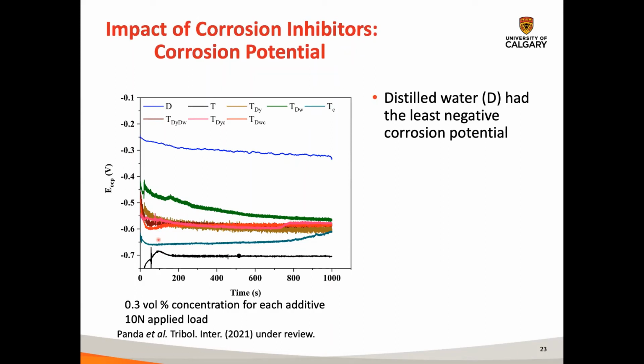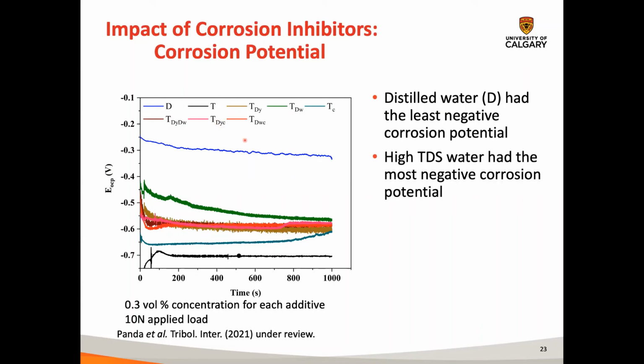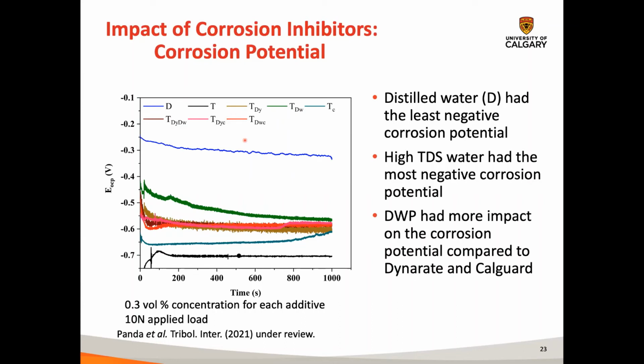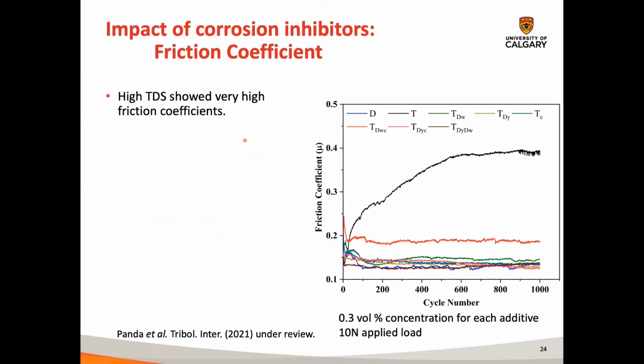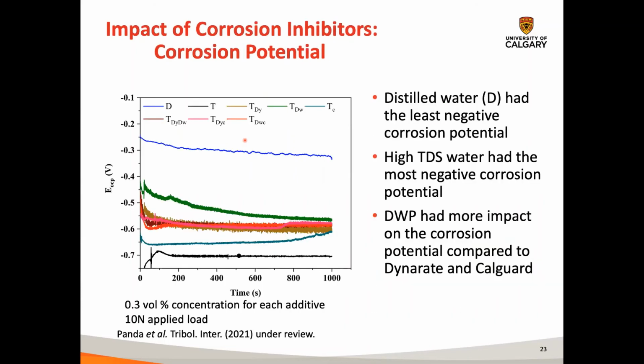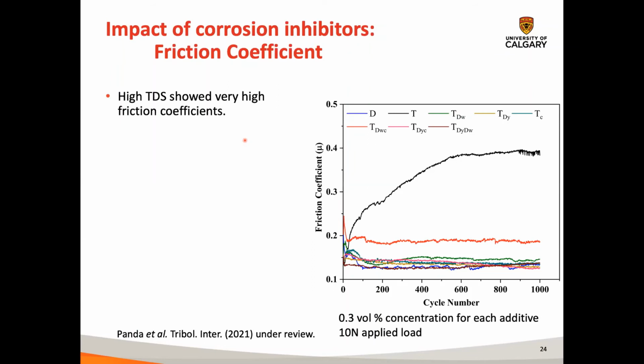And then when we put the different additives in, they did what they were supposed to. So they changed the potential, and so it's less corrosive as you add these different chemicals in. And in this case, we looked at adding both the 2 organic friction modifiers at the same time. And when you see C here, we added the CalGuard and one of the friction modifiers as well. Right, so DWP has more impact on the corrosion potential compared to the other 2 corrosion modifiers. But we'll see later on some interesting results with the friction testing.